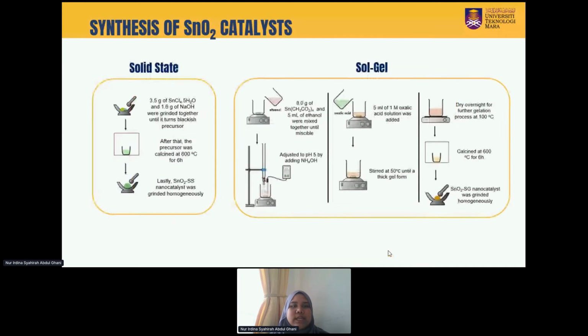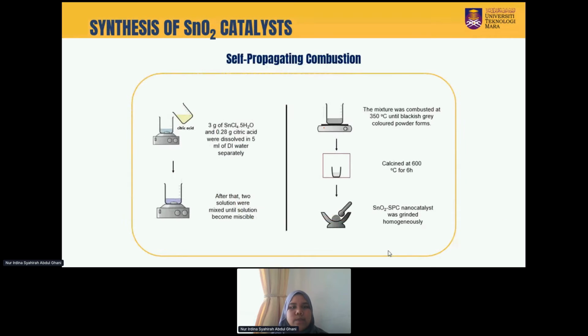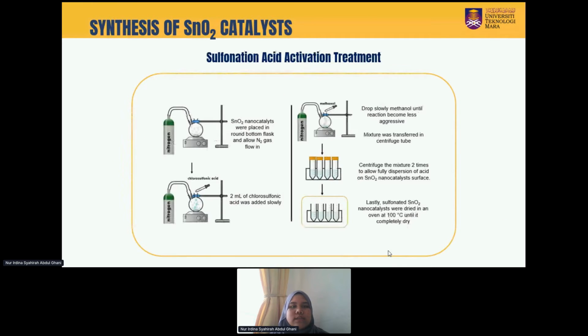All of these three catalysts that have been synthesized, we are going to do the sulfonation acid activation treatment using chlorosulfonic acid, which is way better compared to the other acids, and it is reported that chlorosulfonic acid is one of the high acidity types of acid.